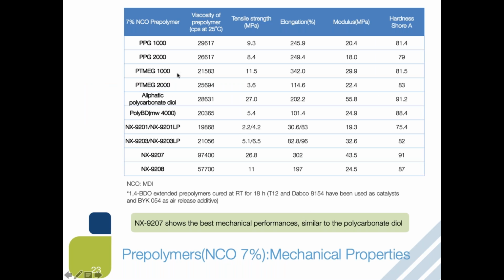In this slide, as you can see, we prepared 7% isocyanate prepolymers using various diols: PPG, PTMEG, polycarbonate diols, poly-BD, and the Carolite products. These prepared prepolymers were cured with 1,4-BDO as an extender, and we used a catalyst and air release to prepare proper specimens, like tensile specimens. When we look at the tensile strength, elongation, modulus, and hardness data, you can see NX9207 has the best tensile strength with elongation quite comparable to polycarbonate diol performance.